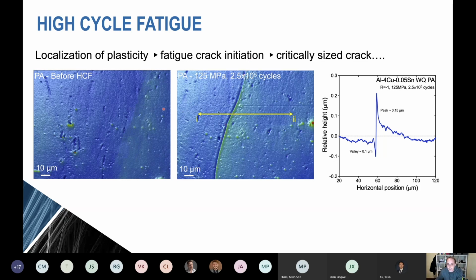And so these are identical regions, and you can see from these little points here. You see them on both cases. And so what that represents there is a massive localization of plasticity in the precipitate-free zone. And what happens in aluminium alloys is this plasticity localizes. It eventually leads to the formation of a crack, and then the material starts to break.